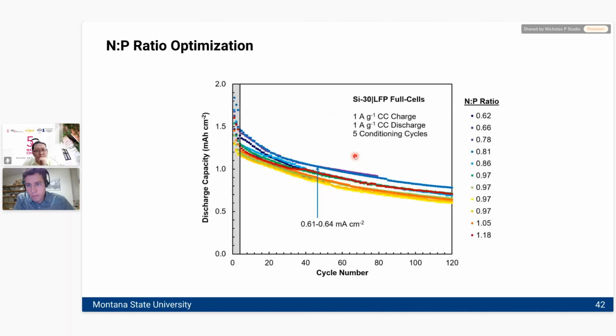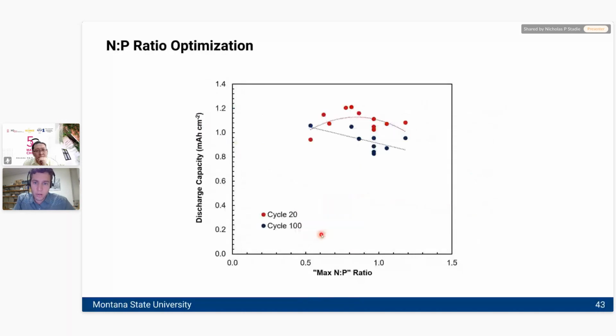Here we have the same data shown in areal capacity, so this is on a per square centimeter basis. And you can see that maybe there's a possible case to be made for a maximum in the areal capacity as you go to just the right thickness. But at the end of the day, it's all pretty close, and the anodes don't perform a lot differently depending on areal capacity as you load them up.